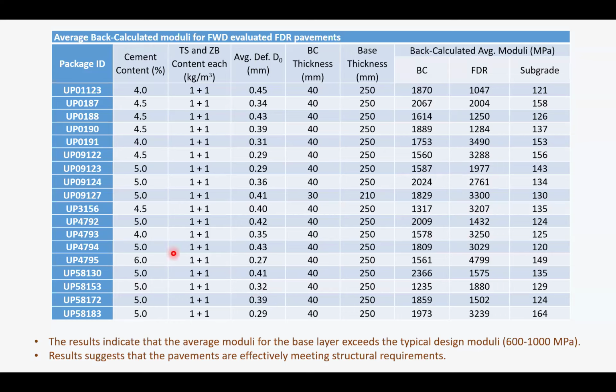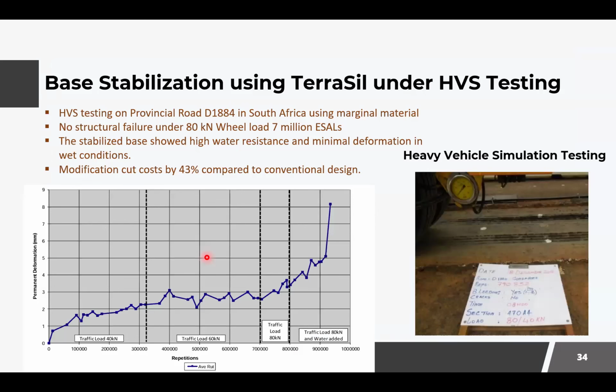Overall, these results indicate that the moduli exceed the typical design modulus that we are considering. That is because we have considered the safety factor of 20%, based upon the empirical equation. So this result suggests that the pavements are effectively meeting the structural requirements they were designed for.